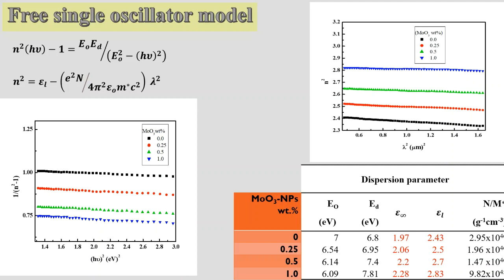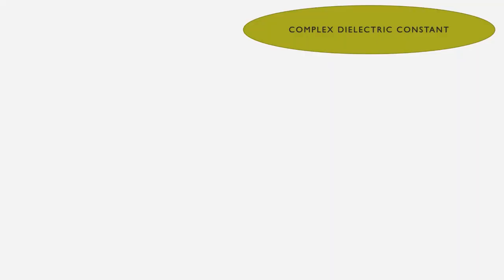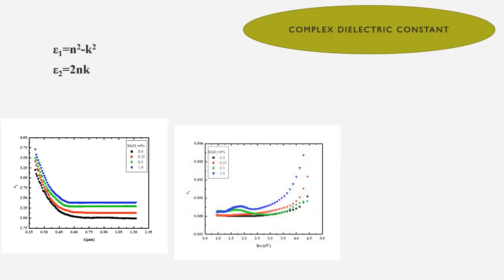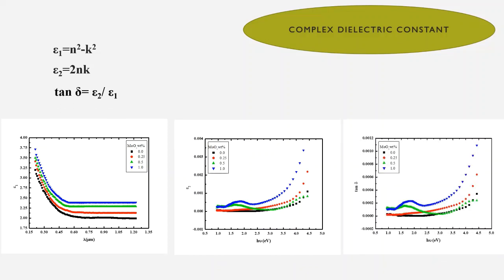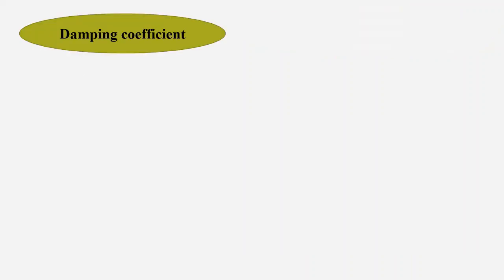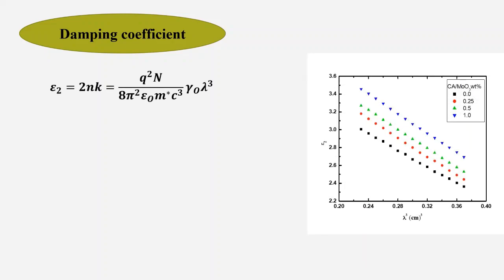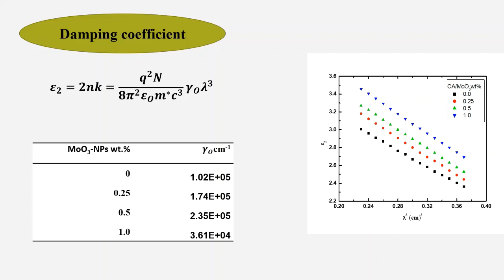We calculate also n over m, which was observed to decrease with increasing the molybdenum trioxide nanoparticle concentration. We studied complex dielectric constant epsilon 1 and epsilon 2 and tan delta as a function of wavelength, and their shapes. We studied damping coefficient from this equation and from the relation between epsilon 2 as a function of lambda cube. From the slope we get damping coefficient, which is indicated here.